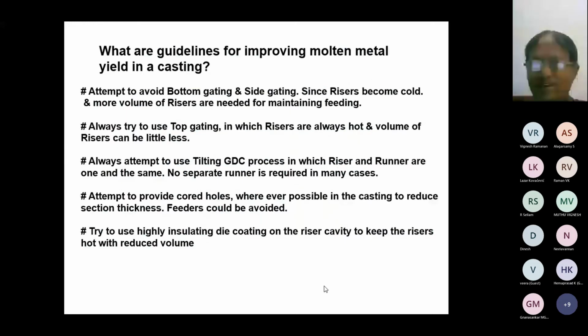What are the guidelines for improving the molten metal yield? Attempt to avoid bottom gating. As far as possible, do not go for bottom gating and side gating, since the risers become too cold and more volume of risers is needed for maintaining the same amount of feeding. Always try to use top gating, in which risers are always hot and the volume of risers can be a little less. Always attempt to use the tilting gravity process, in which the riser and runners are one and the same. You don't have to have a separate riser and runner, both are the same.